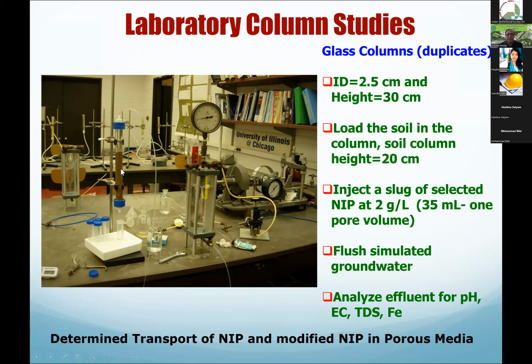So basically, what we did is we prepared the sand column, and then we injected a certain amount of nano iron particles. So let's say 2 grams per liter concentration, and 35 milliliters is the 1 pore volume. So if I flush that one, how much is coming out. And then, we put that on the top, and then we flush the simulated groundwater, and then we analyze what is coming out, pH, EC, TDS, and iron that's coming out through this one. So if iron was transporting through the sand, then you would get those things in the effluent. If it is not, then you will not see the concentrations in the effluent. So very simple, the setup here.